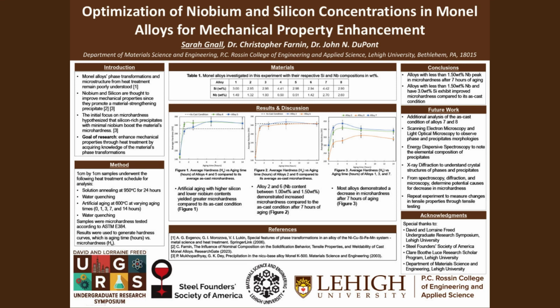The reason this was done is because time plays a critical role in the relationship between mechanical property enhancement and precipitation formation. Therefore, the times chosen were 0 hours, so no artificial aging at all, 1 hour, 3 hours, 7 hours, and 14 hours. After artificial aging, samples were then water quenched again. As mentioned previously, the initial focus on this work was microhardness. Therefore, samples were then microhardness tested, adhering to ASTM standard E384. Each sample received 25 indentations for each aging condition, and then plotted to generate a hardness curve.